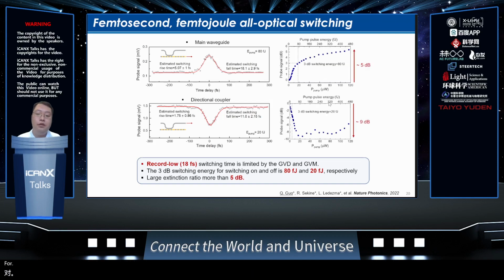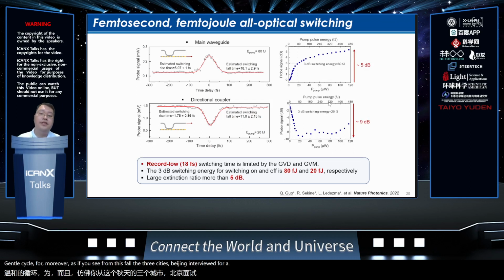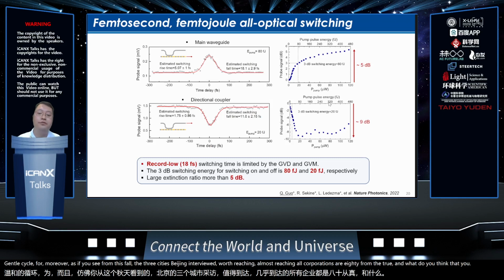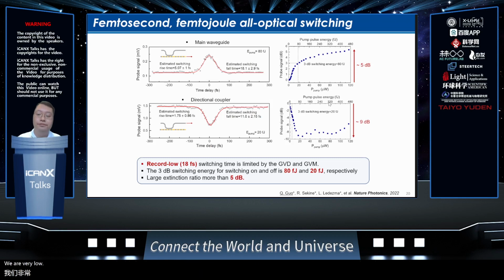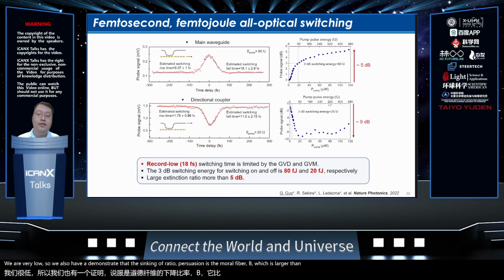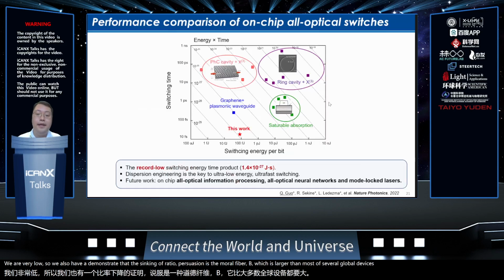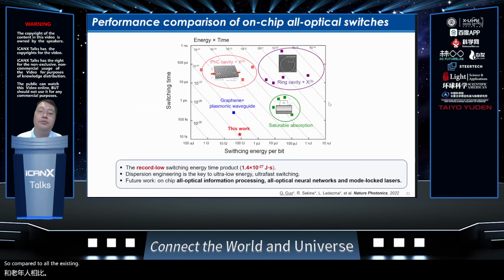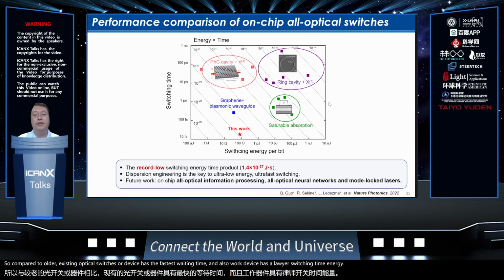So moreover, as can be seen from this plot, the 3 dB switching energy for switching on and switching off operations are 80 femtojoules and 20 femtojoules respectively, which are very low. So we also have demonstrated that the extinction ratio per switch is more than 5 dB, which is larger than most of the existing devices. So compared to all the existing optical switches, our device has the fastest switching time, and also our device has the lowest switching time energy product.